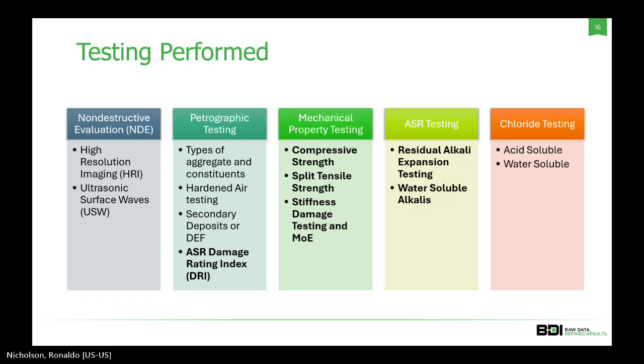He was one of the subject matter experts for the project. So the testing performed, again, we did a lot of testing for this investigation of the north approach. We did some non-destructive evaluation, high-resolution imaging, and ultrasonic surface waves. We also did some petrographic testing to look for the types of aggregates and constituents, hardened air testing, secondary deposits or DEF, and ASR damage rating index or DRI. For the mechanical properties, we did compressive strength, split tensile testing with modulus of elasticity. For the ASR testing, we did residual alkali expansion testing and water-soluble alkalis. And for the chloride testing, we also did acid-soluble and water-soluble. Again, we're not going to go over all of these because it's a very in-depth investigation. We'll only go over primarily the ones that are bold on the screen.